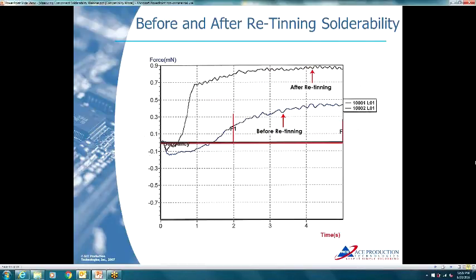That would be a case where it would be very difficult to solder that part in the board, if at all. We took, I think it was 10 or 20 samples, and we retinned them, or basically stripped off the original plating or tinning that came from the component supplier, put a new fresh coat of solder on, and did a second wetting balance test, and you can see the line in black. The meniscus rose very quickly, and you can see the before and after difference, the advantage of retinning a part as far as solderability.